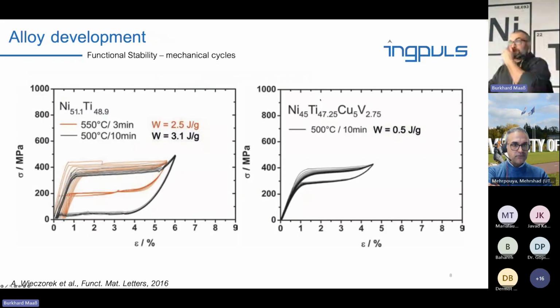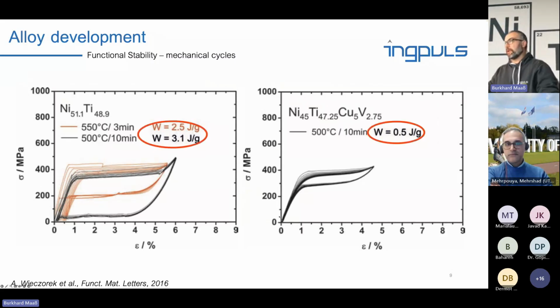He compared this with some binary NiTi and did also some mechanical cycling. You see again here, there is some fatigue, there is some residual strain, even though depending on the heat treatment, on the condition, you can also improve binary material, you can stabilize it. But here you see almost no residual strain, which is really good. What is very important here is that the work output here is a lot bigger for the binary material. So the work required to do a full hysteresis loop is much bigger.